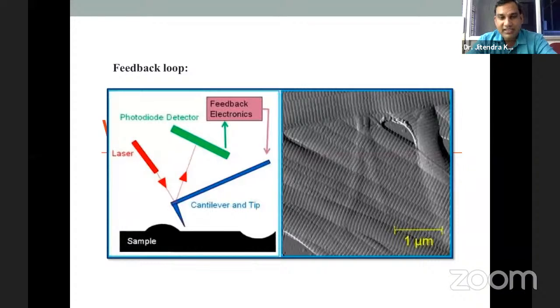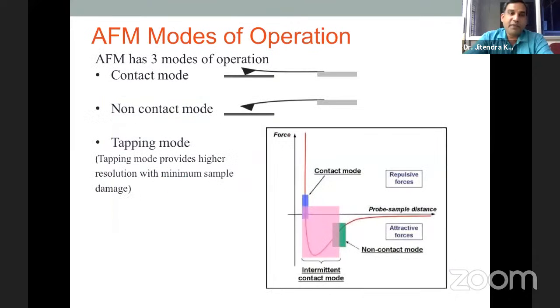So nobody is ready to give you that particular easily, because the tip can only scan in contact mode 1 or 2 times. When your tip is moving, this force displacement curve is formed, and this deflection happens, and due to the adhesive forces between the tip and the sample surface, the weak van der Waals forces, it can detach from the surface.